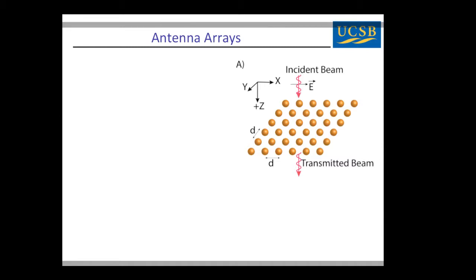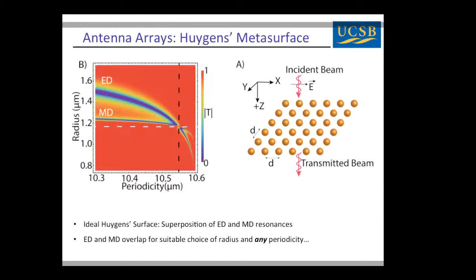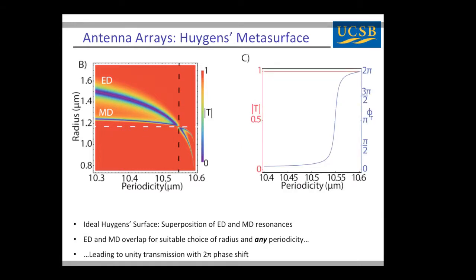Well, here now I'm going to go from these single particles to looking at arrays of these spheres. We can see this is a plot of transmission as a function of the radius of the sphere and the periodicity of the array. And what you'll notice is that if we're detuned from the electric and magnetic dipole resonances, right? So this was that spot I said where the amplitudes and phases of the two modes are equal. And so this white line that I'm showing is a trace where if you change the periodicity, we can have unity transmission, but our phase goes through a 2-pi phase shift. Okay? So this is the basic kind of idea that we're going to use,